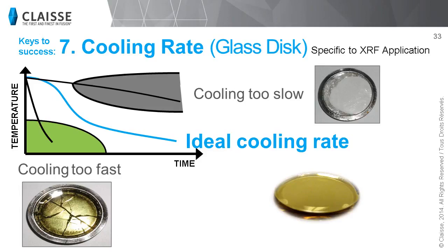If you cool it too rapidly, you will induce stress in the glass, thus making it crack in the mold. On the other hand, if you cool it too slowly, you will allow the molecules to reorganize in their lowest energy state, which is crystal, so you will get a crystallized disc. The appropriate cooling step of a glass disc is somewhere in between too fast and too slow. Ideally, you should start to cool the sample slowly, then increase the cooling rate gradually.